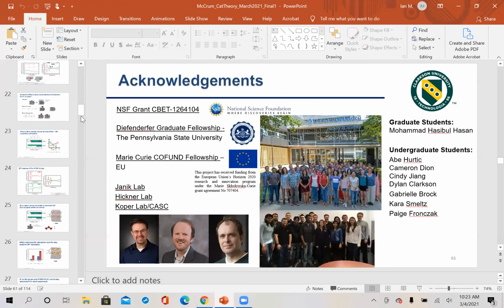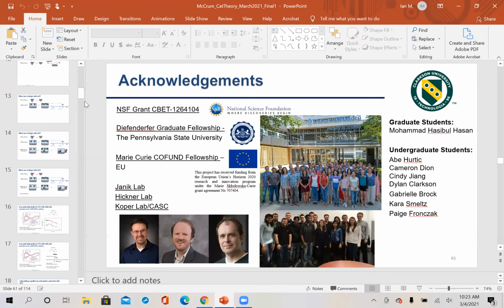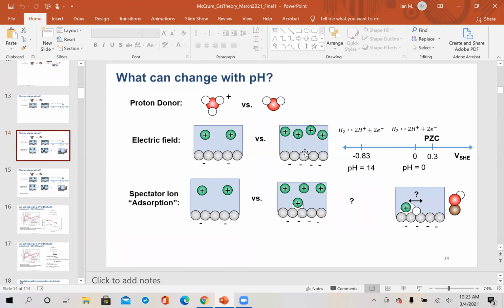Yeah, so I guess there's a couple ways to look at it. The picture that I would give is, if I compare this picture here with this picture here, with this picture here, we're going to have some fairly uniform electric field across the surface. It's going to be dictated by pH and concentration of the cations, thickness of the double layer, all that stuff. However, when we look at this close approach of the cation, I would now imagine that the local electric field close to the adsorbate is now much more complex because these cations retain most of their charge on adsorption. And so I expect it's mostly an electrostatic effect.